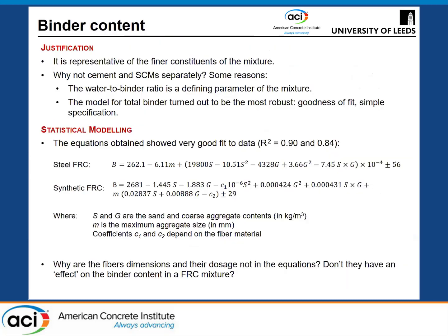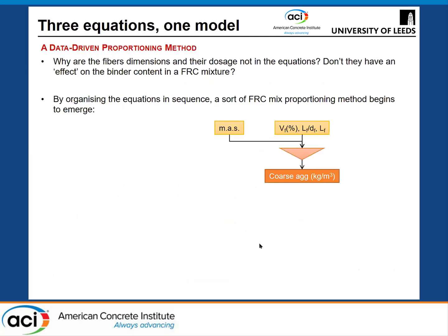And finally, we did the same with the binder content. So trying to predict the binder content as a function of the other parameters in the mix. And we obtained equations that were very, very accurate in terms of fitting the database. And again, it's important to remember that these R-squared values look high, but this is even more significant when you consider that you're talking about mixes obtained from more than 100 different papers produced by different authors, and they are relatively simple. So this is very powerful.